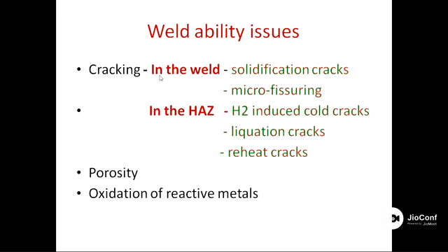So if the weld pool is not protected from the atmosphere, and hydrogen gets diffused into the structure in the heat affected zone, then hydrogen induced cracking, or say cold cracking, can take place. Or liquation cracking is another phenomenon. It happens because of the presence of low melting point metals. And reheat cracks take place particularly with chrome moly steels and creep resisting steels. Other issues are porosities: welding of aluminum will end up with a porosity problem, and oxidation of reactive metals like aluminum, chromium, molybdenum. They are very reactive to oxidation.